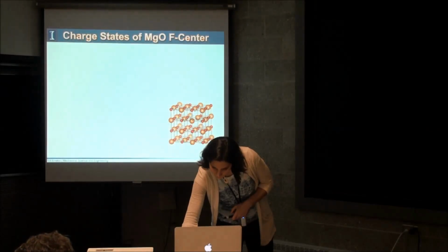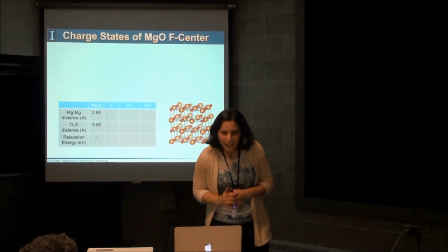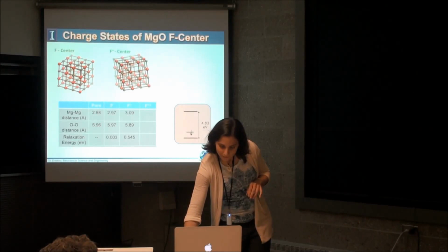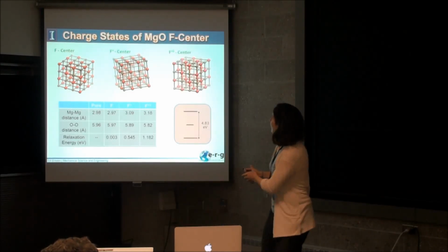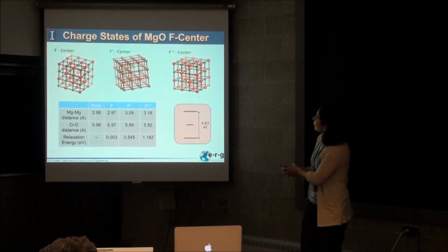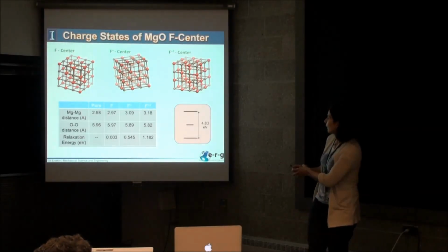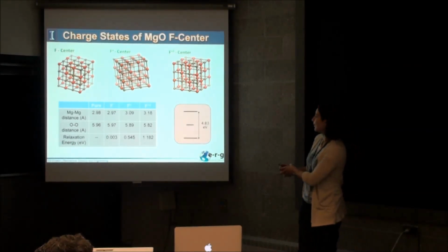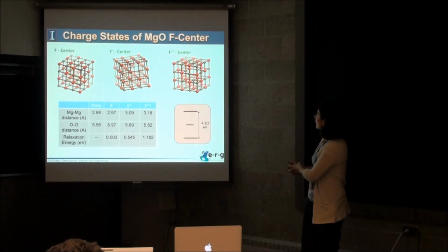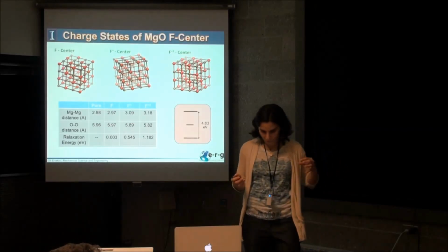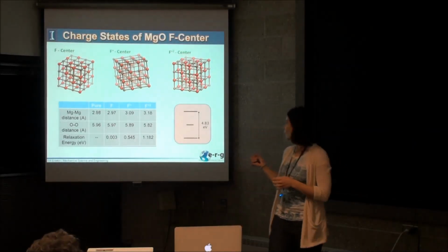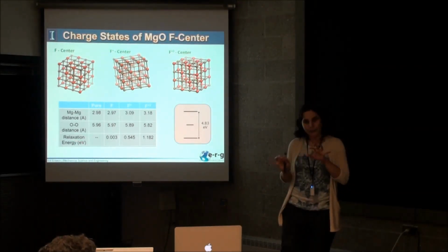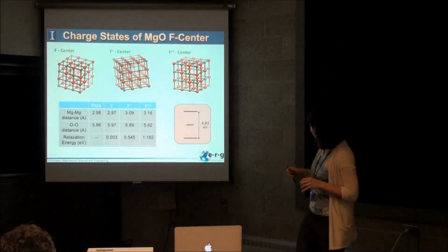And so what we've done for this particular system is we actually had to use a little bit of DFT and a little bit of quantum Monte Carlo. We used DFT to predict the local relaxations that take place around this missing oxygen atom, right? That's the defect that I'm looking at, a missing oxygen atom. It's called an F-center defect, a Farb center, in different charge states. I use DFT to predict the relaxed structure of the atoms around that defect. Can't do that in QMC, not yet.